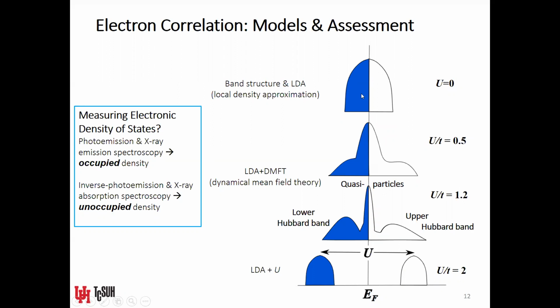So we can somewhat measure these, well, I'm going to be careful here. We can assess electron correlation, okay, if we use tools that can detect this type of filled state density of states and empty density of states. And there are a couple of ways to do that. Photoemission, for example, like angle resolved photoemission, can measure filled density of states. These are electronic states. X-ray emission can measure a signal that is proportional to the filled density of states, okay? And techniques like inverse photoemission or X-ray absorption can give you signals that are proportional to unoccupied density of states.